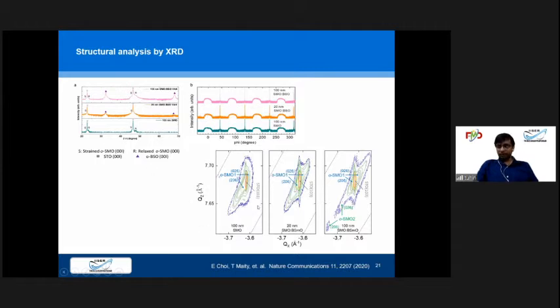Now we did a detailed XRD, called a reciprocal space map, to identify how the crystal structure of the samarium manganese oxide has been changed due to the STO. As we can see, we deposited different combinations of material. One is only samarium manganese oxide, so these are only columns, no matrix. This one is thin samarium manganese oxide and bismuth samarium manganese oxide, so thin band material. And this is thick. As you can see, only samarium manganese oxide does not have any out-of-plane strain. The thinner film also does not show any out-of-plane strain. But as we increase the thickness, another secondary peak started coming out, which is basically due to the additional strain we are getting in the thick film.